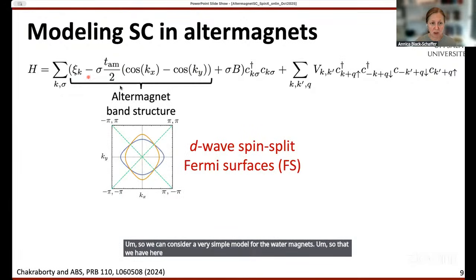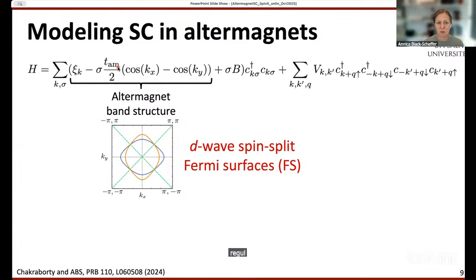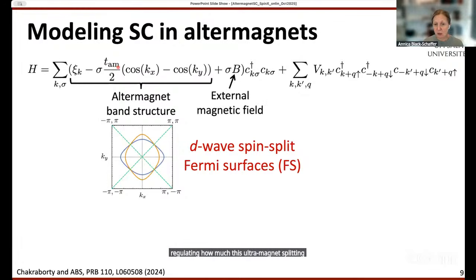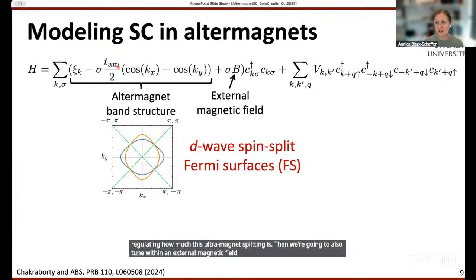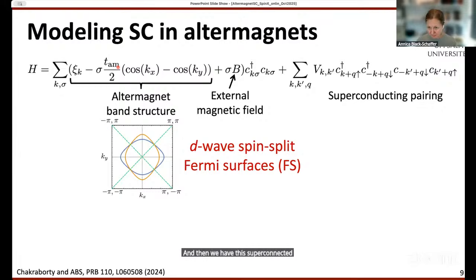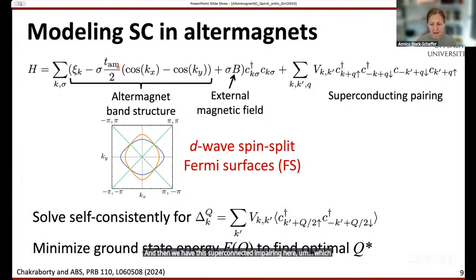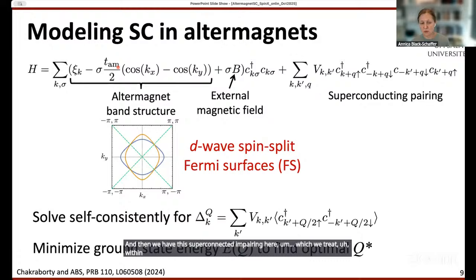So first we have a term here that's just going to give us an altermagnet band structure, and more specifically an altermagnet Fermi surface. So here's this D-wave spin split Fermi surface that we get by tuning this TAM, which is sort of regulating how much this altermagnet splitting is. Then we're also going to tune with an external magnetic field to see if that changes things. And then we have the superconducting pairing here, which we treat within mean field theory, as we usually do.